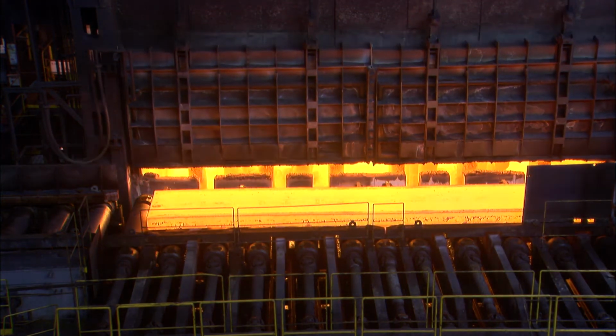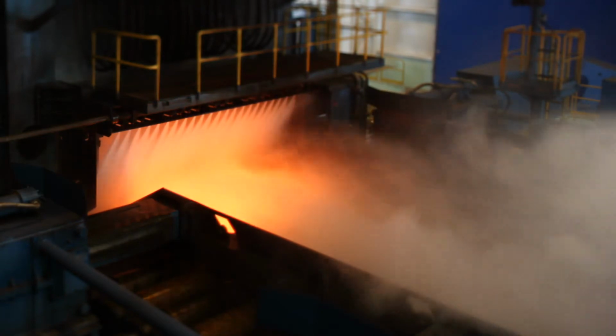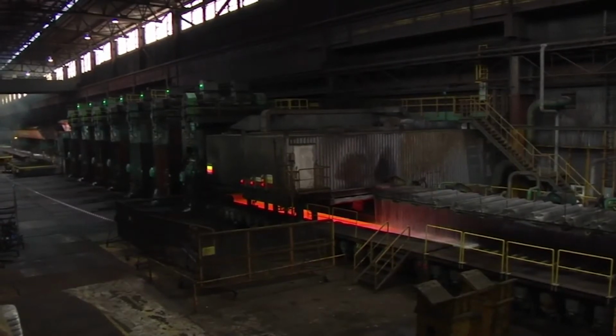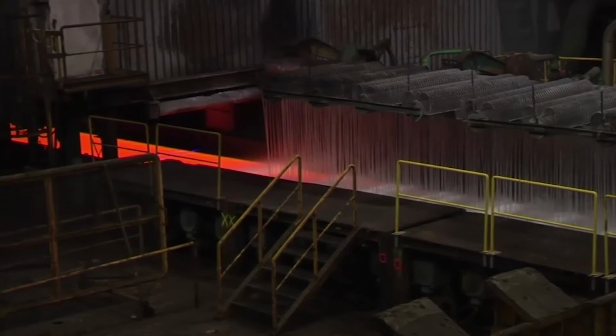The most difficult property to be achieved on pipeline steel in heavy gauge is toughness at low temperatures. This property is tested by Battelle drop weight tear test, and this test mainly depends on fineness of the microstructure and homogeneity of microstructure. This property can be very well mastered by careful control of the thermomechanically controlled process, and traditionally during this process it is aimed towards high strain accumulation, which follows afterwards with accelerated cooling. Therefore, we have to carefully choose the processing parameters in order to master these properties.